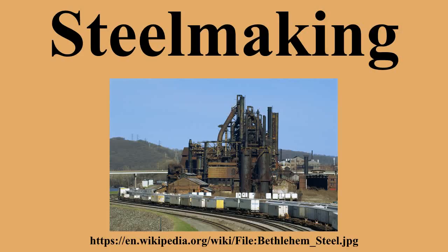Between 1920 and 2000, labor requirements in the industry decreased by a factor of 1,000, from more than 3 worker hours per ton to just 0.003. The vast majority of steel manufactured in the world is produced using the basic oxygen furnace. In 2011, it accounted for 70% of global steel output. Modern furnaces will take a charge of iron of up to 350 tons and convert it into steel in less than 40 minutes, compared to 10 to 12 hours in an open hearth furnace.